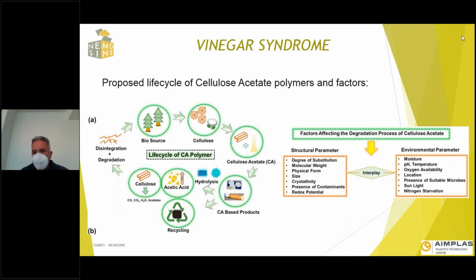The main problem of these external factors is that to reduce the speed of the vinegar syndrome process, we need to reduce, in a very big way, the external factors that affect this reaction. This means, for example, that in the archive they are using very low environmental temperatures. They have important systems to reduce the temperature of the environment to between 1 degree, 4, 5, 6 degrees, not more. As you know, this represents a huge consumption of energy per year. If we develop, and this is the main goal and objective of the NEMOSINE project, if we reduce the energy requirements to reduce the speed of the vinegar syndrome, we achieve an important objective.